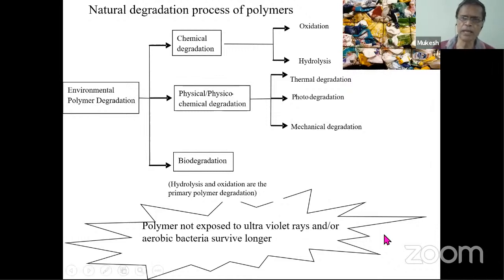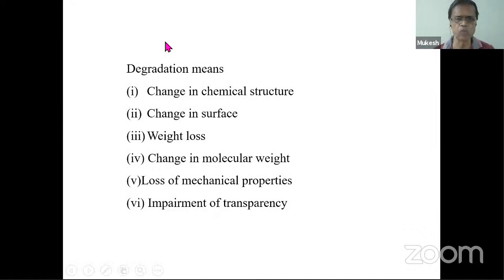Okay, so for floating material, the chances of degradation are much higher than for material which is sunk to the bottom of the sea, because there is no heat and it is not exposed to UV light. UV light helps to degrade the bonds in the polymer chain and helps for the attachment of the organism and for the degradation. Okay, so degradation means what? It is not breaking of the material, that's called deterioration. Microplastic is not degradation of larger polymer. Microplastic is deterioration of larger polymers because of ocean currents and wind velocities.